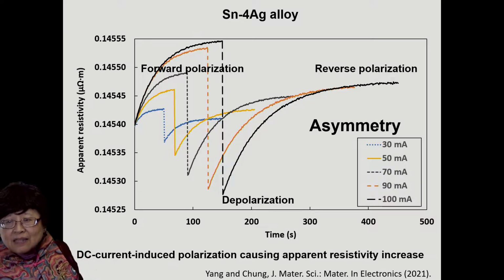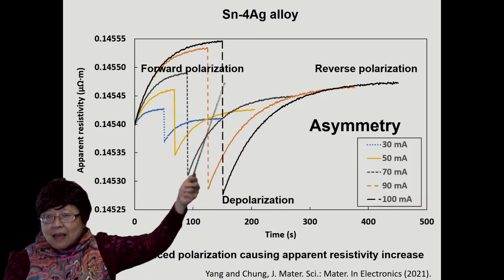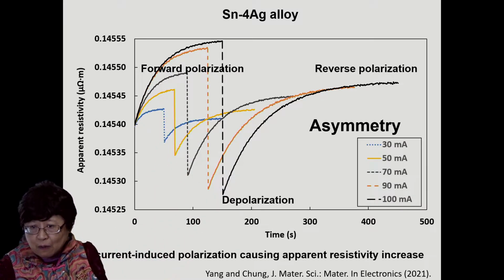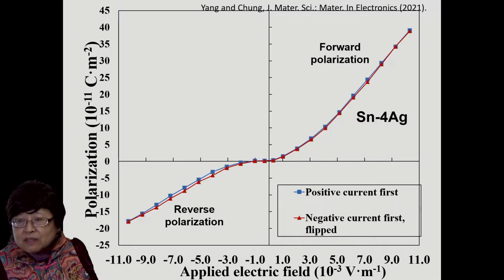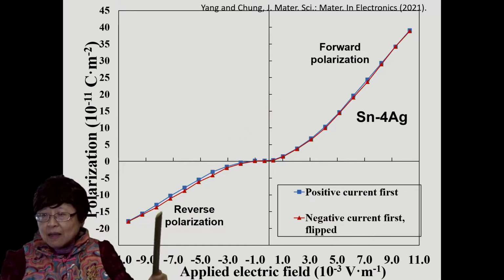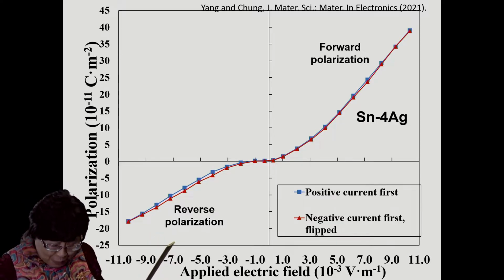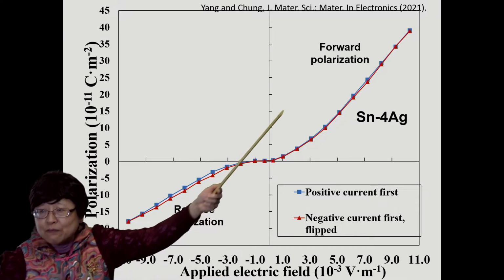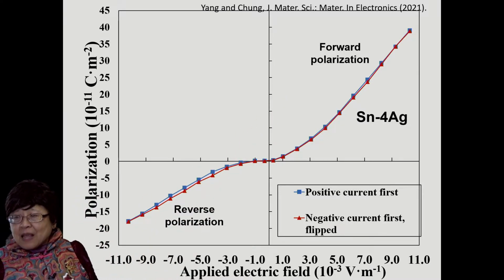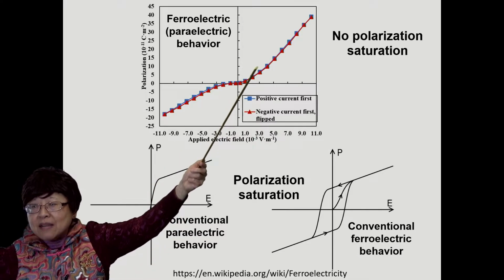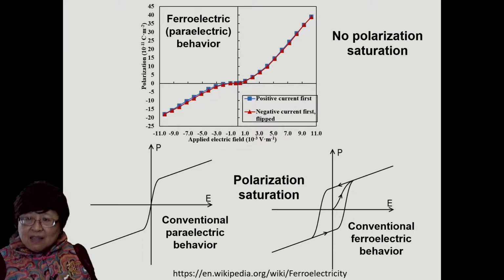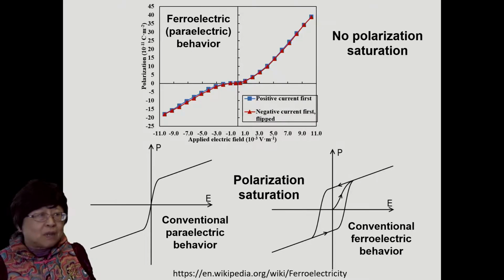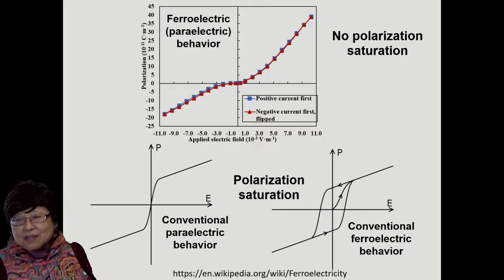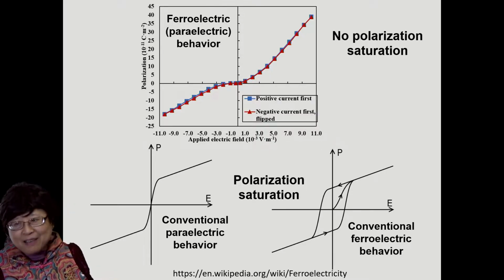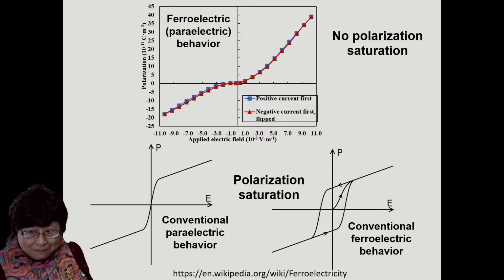Obviously, the higher the current, the more is the effect. Note that the reverse polarization is less than the forward polarization. There's asymmetry involved. In other words, the forward polarization is more. The forward and reverse polarization are opposite in direction, but the magnitude is more for the forward than the reverse. And interestingly, there's no polarization saturation. It keeps going. The polarization keeps increasing as the applied electric field increases. So this is ferroelectric or paraelectric behavior, whatever you like to call it, in a metal.